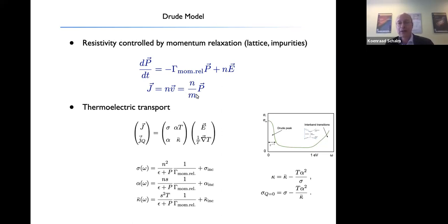You get a very simple theory of thermoelectric transport, which is Drude theory, which underlies this very simple picture of ordinary metals that we have seen, right? And in a slightly generalized version where you make this non-relativistic version relativistic, the result that you get out of Drude theory has the following form. This is the part that's dominated by the momentum relaxation rate. If the momentum relaxation rate is very small, this dominates. This is the Drude peak. And then there could be a so-called incoherent, an intrinsic, contribution to the conductivity as well.